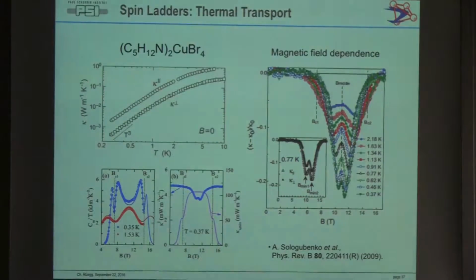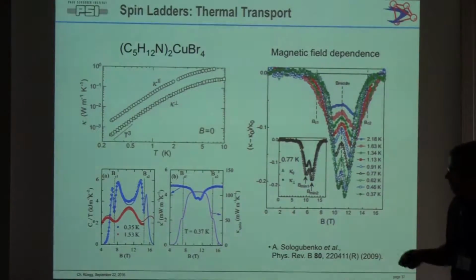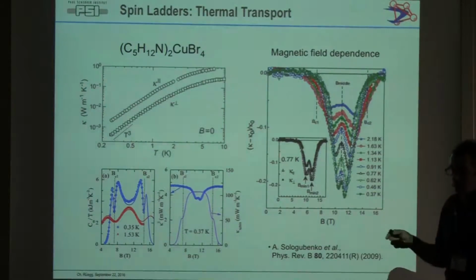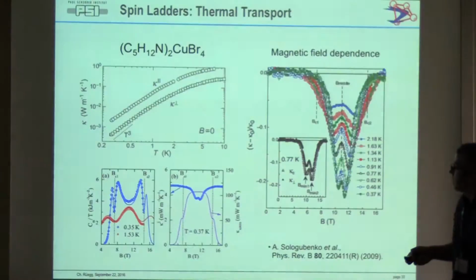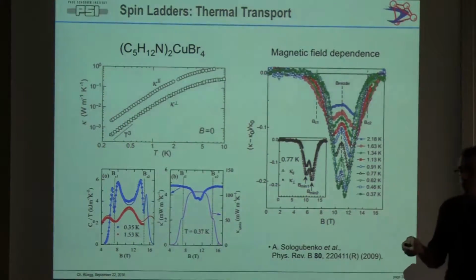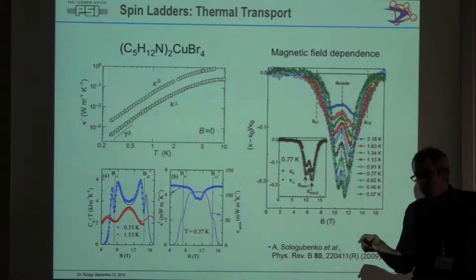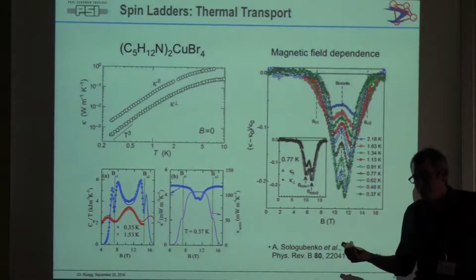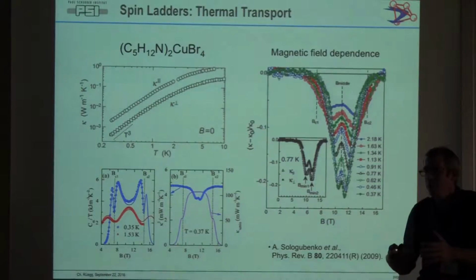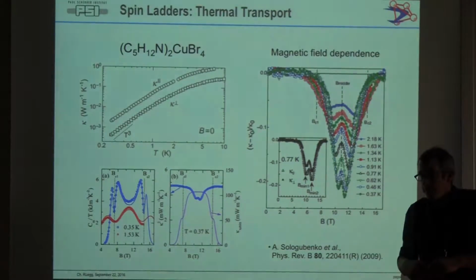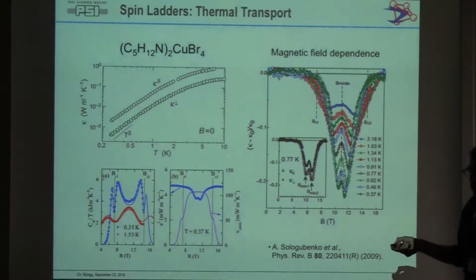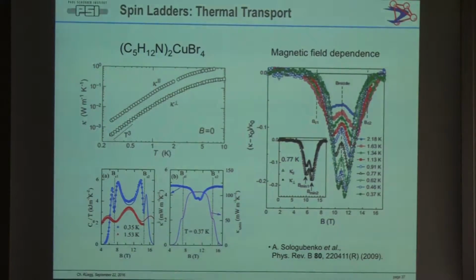But are we sure that the lattices are not somehow weakly coupled? They are very weakly coupled. We know, for example, in the Luttinger picture, I have a phase diagram a bit later, which I'm not going to be able to show, but the Luttinger liquid picture starts at something like 1.5 Kelvin, and if you cool to 100 millikelvin, you see that actually 3D order appears. So there's very weak coupling between the chains. Yeah, but you are at very low temperatures there. It's 300 millikelvin, but it's only at 100 millikelvin that the 3D coupling is strong. But for your argument, you are above the 3D ordering temperature, by a factor of 3.